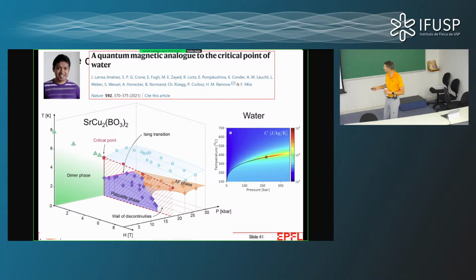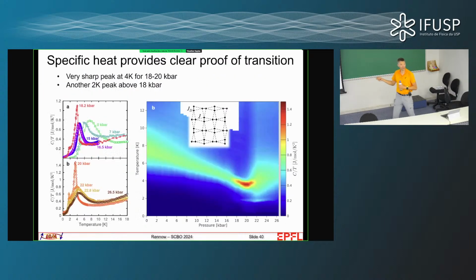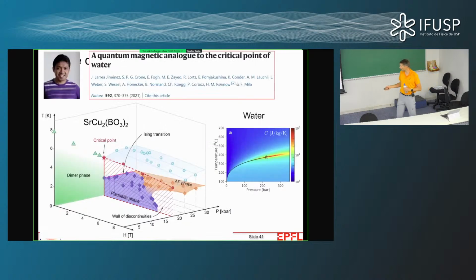But if you look at the specific heat at this critical endpoint and around it, you have a huge enhancement of specific heat. And this enhancement in specific heat is exactly the same as the enhancement that Julio discovered in borate. So what we have is a quantum magnetic analog of the critical endpoint of water, where we go from the dimer phase into this plaquette phase, and if we go up in temperature, we can go around this temperature and pressure without ever crossing a phase transition. If we go down to lower temperatures, like this, then we cross the phase boundary, and then we see the critical line. So we actually understand, and these experiments with specific heat were really the proof that we are in a new phase of this material.